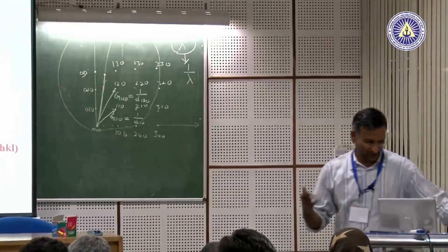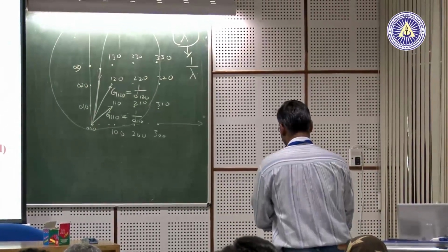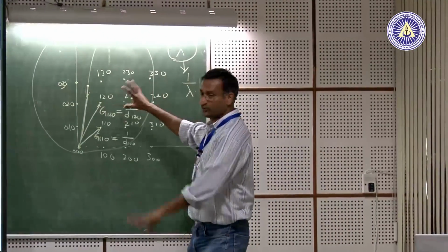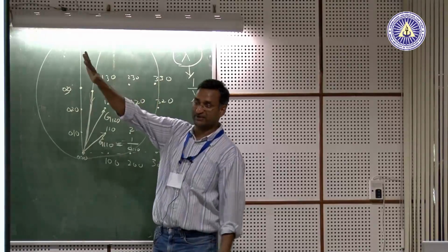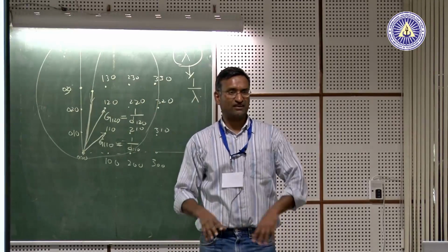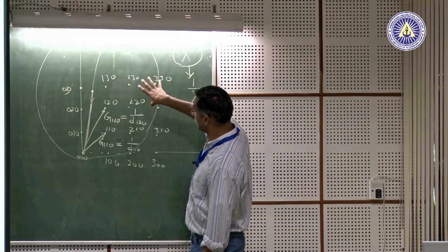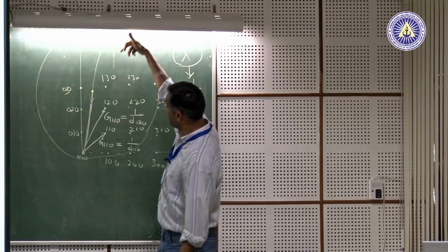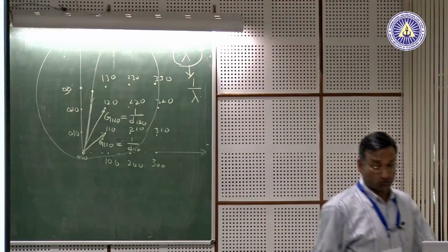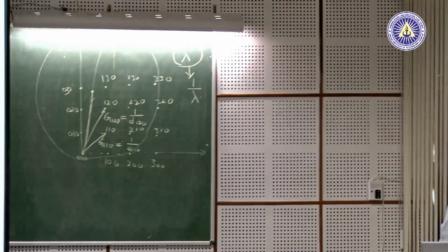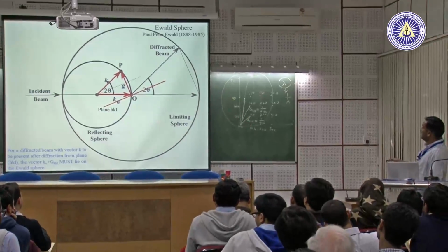I mean, it is possible for polycrystals as well, but it is easier to represent in the case of single crystals than polycrystals, because in polycrystals the reciprocal space will be all mismatched, because one lattice will be in this orientation, another will be in some other orientation. As a result, you will have too many reciprocal lattice points for a polycrystal. Let us say this is a single crystal, this is the reciprocal space, and you have a beam coming along a certain crystallographic direction.